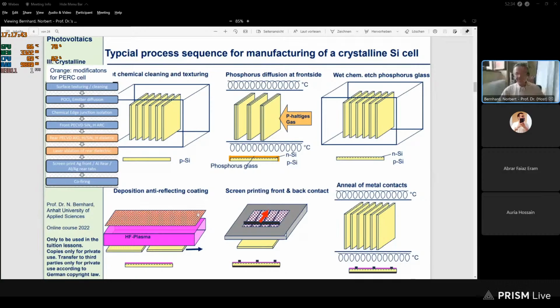In the next step, we make the metal contacts by a screen printing process at the front and back side. You see here is symbolized the front side. On the front side, we print these fingers and bus bars. On the back side, for the standard cell, we print just the whole area aluminum layer. And the final step is an annealing of the metal contacts. This is a step which really makes the contacts. And you see also in this case, the contacts have to be etched through the anti-reflective coating, because the anti-reflective coating is an insulating dielectric, and therefore, of course, the metal of the fingers, or the silver of the fingers, must get into contact with the semiconductor material to make this contact.